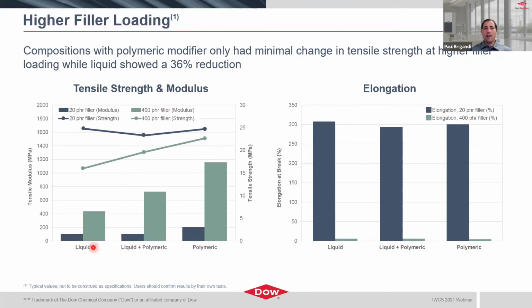And what we want to point out, I think the key here, is we're looking at 20 parts filler versus 400 parts filler. So a dramatic difference to highlight how the filler impacts the performance, as well as highlight the different modifiers. I think 400 is an exaggeration, right? I think that's on the very high end of where anything would really be. But again, for demonstration purposes, what we see is an increase in modulus. So that's the bars at 20 and 400 parts. As expected, you see a significant increase and the modulus is much higher with the higher filler loading.